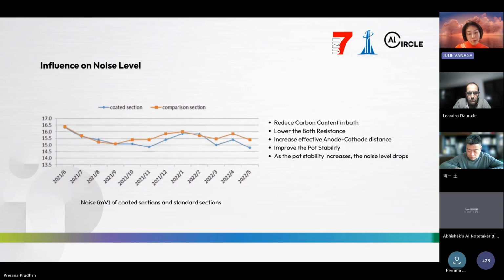So with less carbon residue and less resistance, the effective anode cathode distance is increased and the pot runs much more smoothly and stably. As a direct result, the noise level of the potline, we can see, drops significantly. So for smelters, this means a more stable production environment and less wear and tear on the pot equipment, extending the service life of expensive electrolytic pot assets. Okay, so let's turn to the next page.